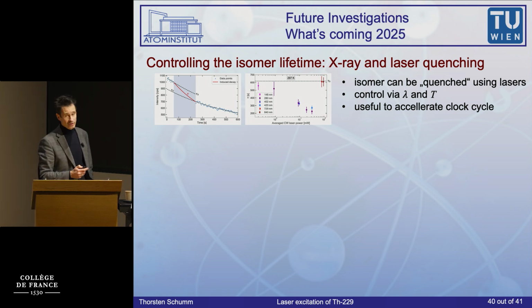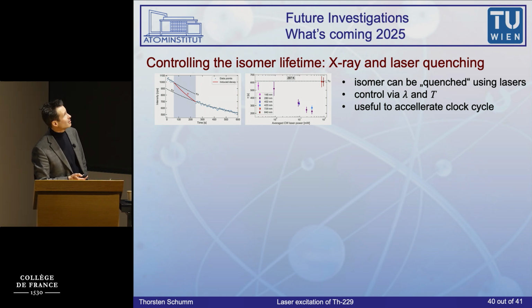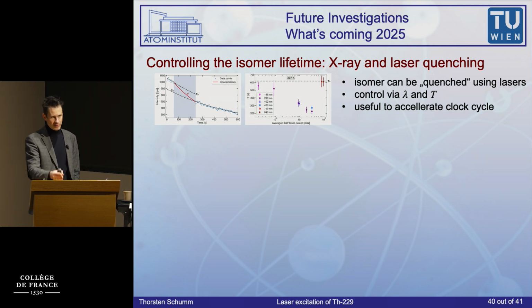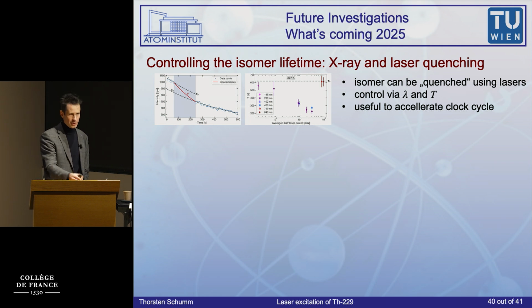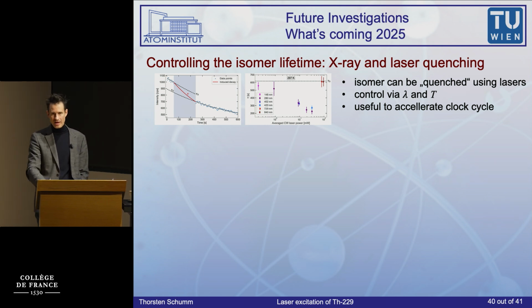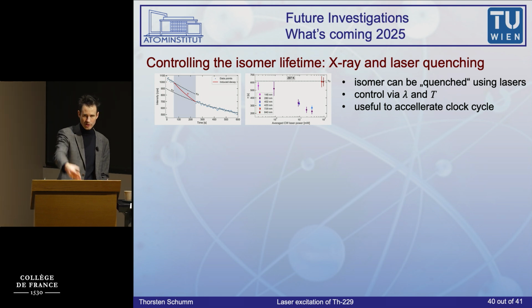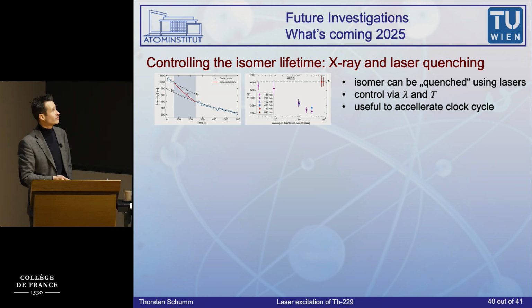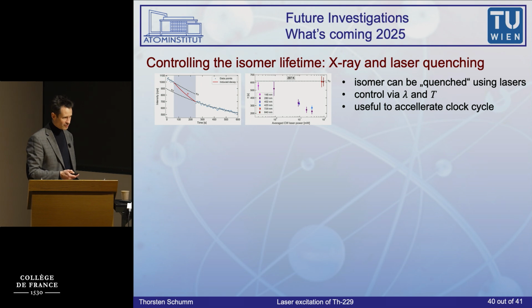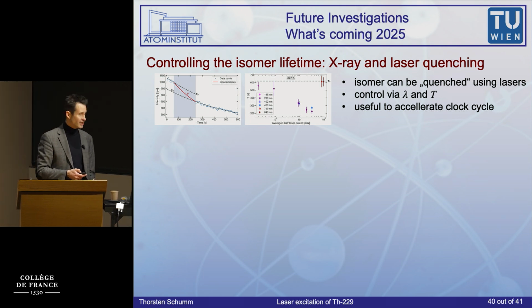And so that's something we're going to investigate a little more, because it's actually quite exciting, and it allows us to speed up these experiments. If I ever want to build a clock that relies on a feedback cycle, having to wait for 11 minutes to see whether my excitation attempt has been successful and then I have to start over again. If I have something that allows me to quench down the isomer to the ground state to reinitialize the system faster, that's actually good for clock operation. So we're looking into this quenching effect and trying to understand what's happening there.